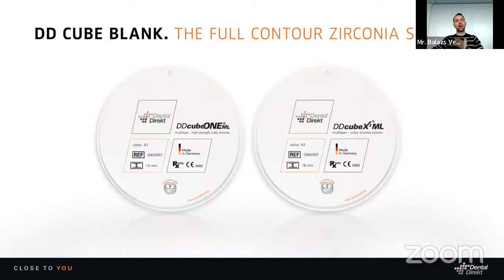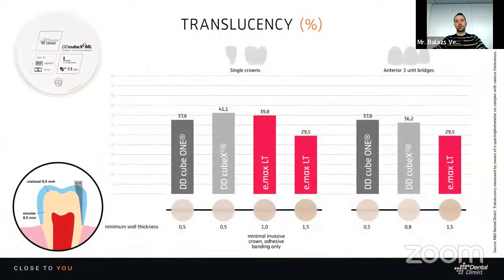Of course, now I wish to introduce our full contour zirconia system. It means the Cube 1 and the Cube X materials, both of which are available in a multi-layer form, and I wish to compare that with a well-known e.max product, a popular product. I wish to introduce that because we are getting more and more requests to develop materials comparable with e.max materials. We analyzed our materials, and we figured out that today with the Cube X and Cube 1 zirconia materials, we can reach the same aesthetic or even better aesthetic than e.max, and, which is a really important thing, with smaller wall thickness.